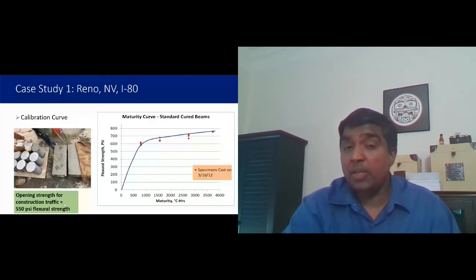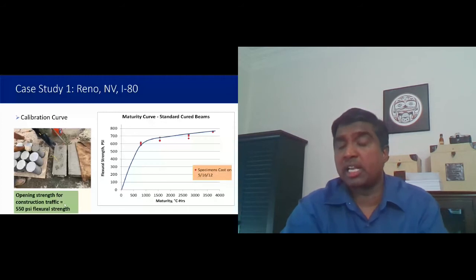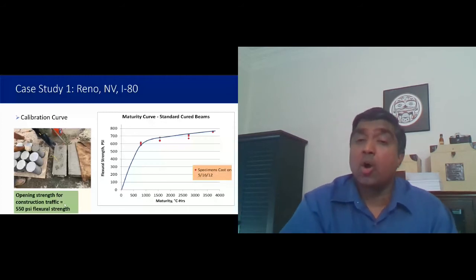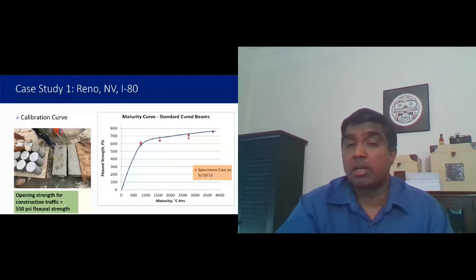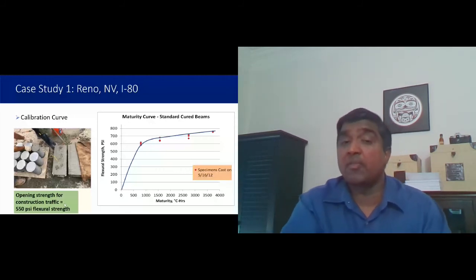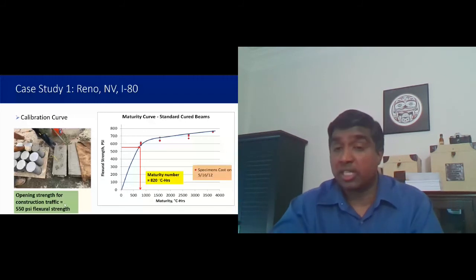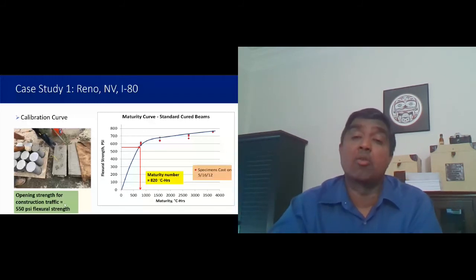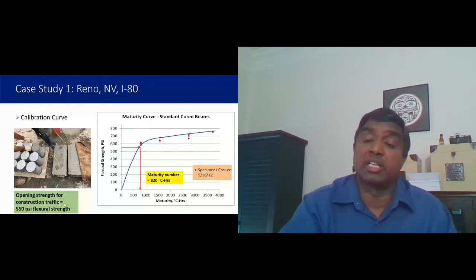So for 550 PSI flexural strength, using this calibration curve, we found that the maturity number for 550 PSI flexural strength for this particular concrete mix is around 820 degrees C hours.